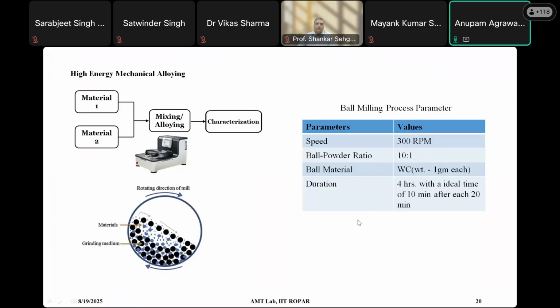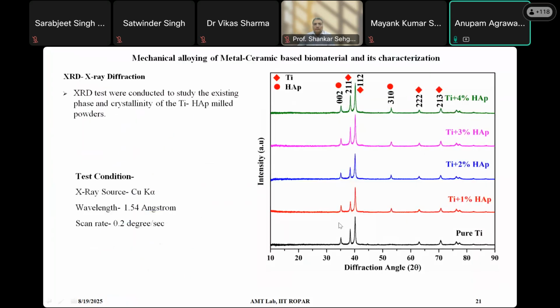After several trials and errors, we could find some ideal parameters for this ball milling process. Then we tried to identify whether the mechanically alloyed metal ceramic powder has all the correct ingredients of titanium hydroxyapatite. So we performed XRD, X-ray diffraction, to study the existing phases and the crystallinity of the titanium hydroxyapatite milled powders.